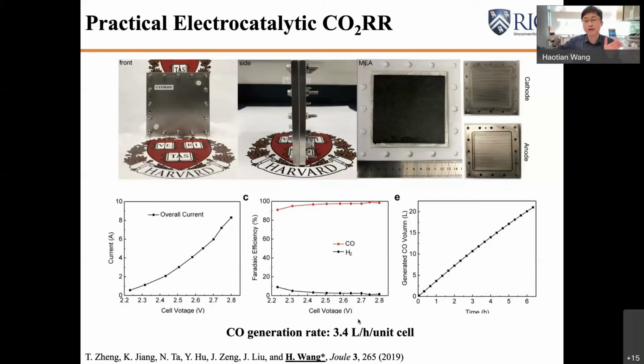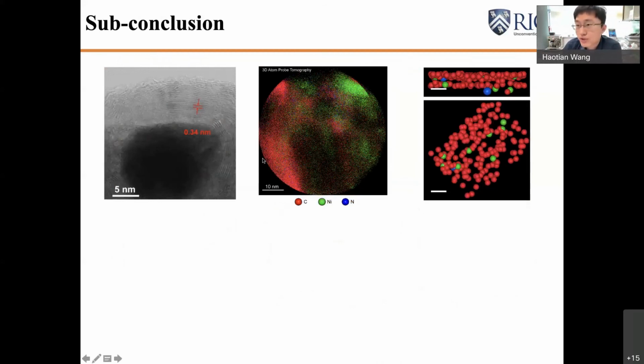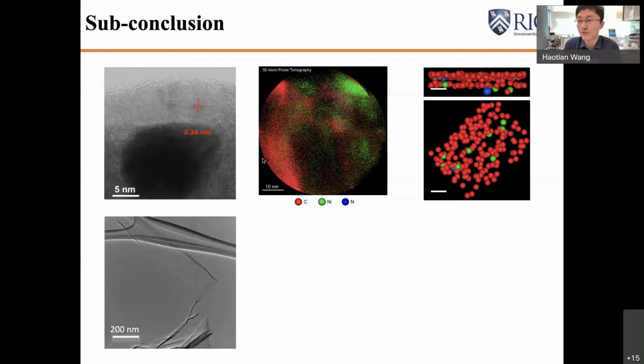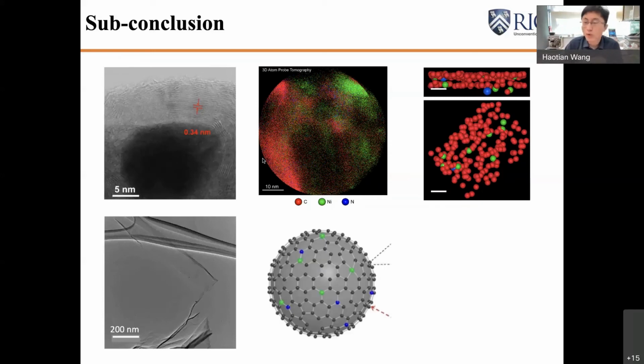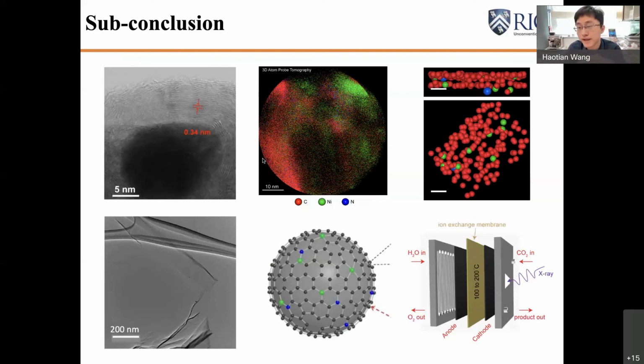And if you want to deliver a high rate of CO, you can simply stack the unit cells into the capacity that you want. And we can make a very small sub-conclusion. These three works actually reflect some of the style of our group's research. We start with a very complicated structure of materials by using different types of advanced characterization tools, atom probe tomography, X-ray absorption spectroscopy. We slowly reveal what's really happening on the surface, what's the real active sites. And then we simplify the design of the catalyst and only magnify the active sites. And then we also want to lower the cost of the material synthesis and also engineer the cell design for better performance.